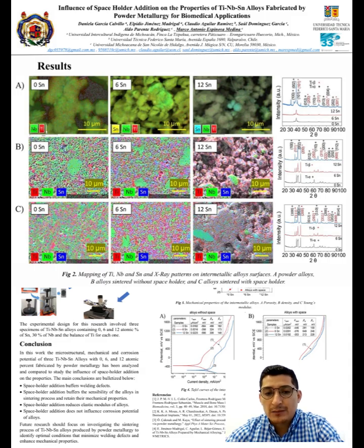In figure 2, the mapping of titanium, niobium, and tin, as well as the X-ray patterns on intermetallic alloy surfaces, are presented. In row A, the micrograph of the powder alloy for 0, 6, and 12 atomic percent of tin is presented. This micrograph reveals a uniform distribution of the elements, and the X-ray patterns indicate the presence of two crystalline phases, a mixture of beta and alpha titanium.